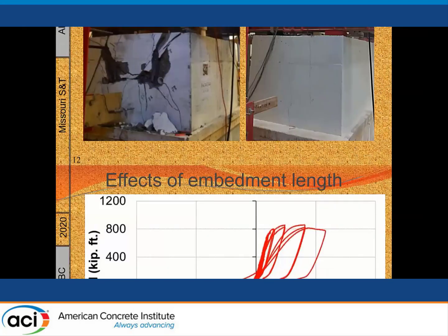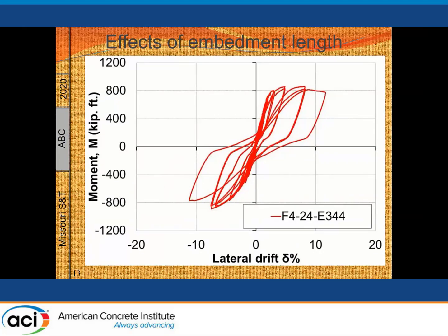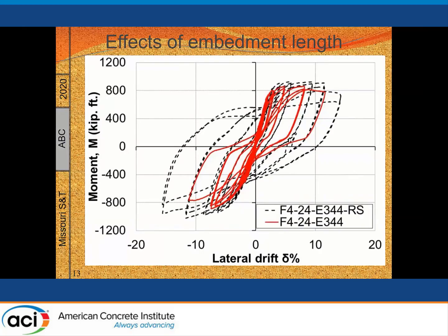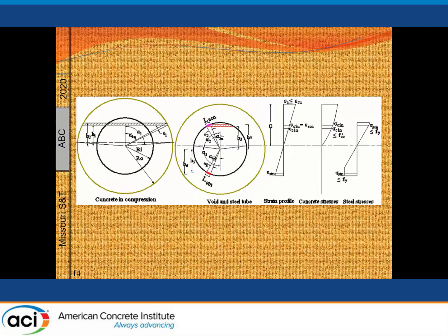The red here is whenever we don't have enough embedment length. Over here, the black one is whenever we provided enough embedment length. So we can tell, well, the strength did not really increase that much, but it's mainly the energy dissipation, with a very fat loop in the case of the black one with the required embedded length.